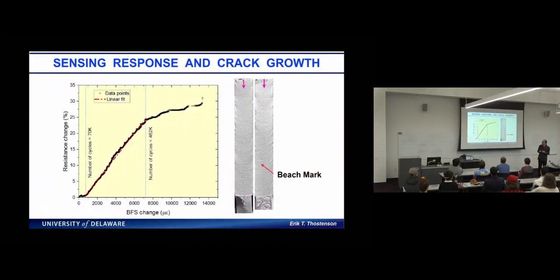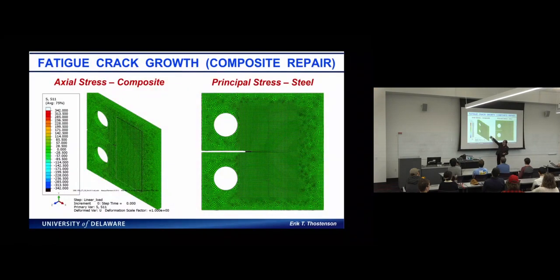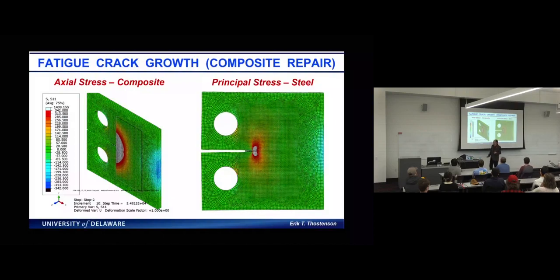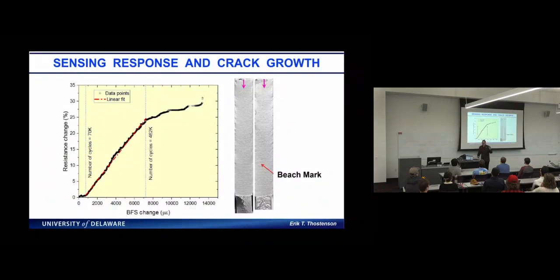And we've looked at, so this is something where we're looking at our change in the electrical properties of the sensor. And this is what we call the back face strain. If you were noticing on this side, in the video, we get a compressive strain on the back. So it's actually a measure of the length of the fatigue crack. And we see almost a perfect relationship between our back face strain and our sensor response.